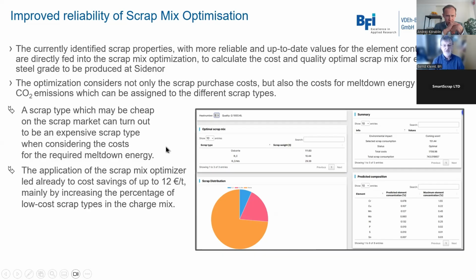So at Sidenor, trials have been performed with the scrap mix optimizer, and these led already to cost savings up to 12 euro per ton, depending on the steel grade to be produced. And this was achieved mainly by increasing the percentage of low-cost scrap types in the charge mix. The better you know the composition of the scrap types, of course, the more you can allow to use scrap types which have lower costs and then also have a higher concentration of tramp elements like copper.